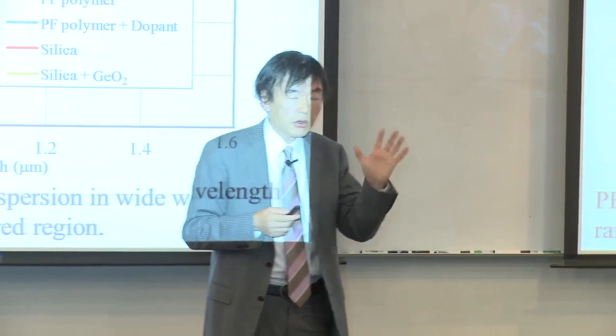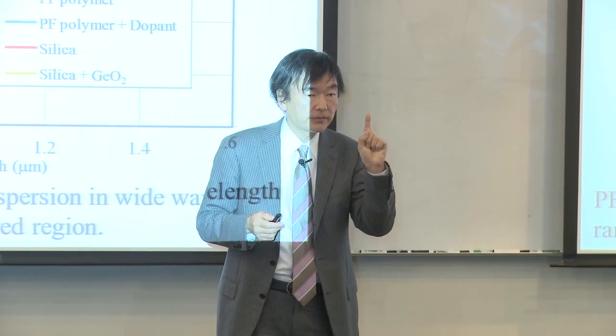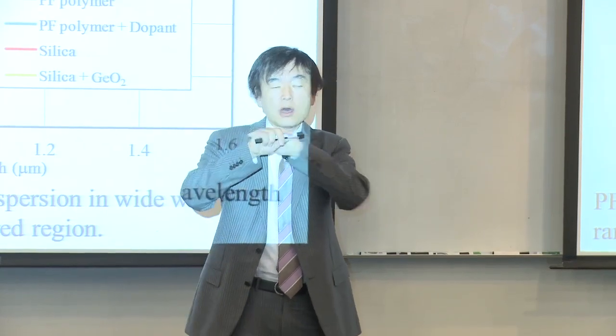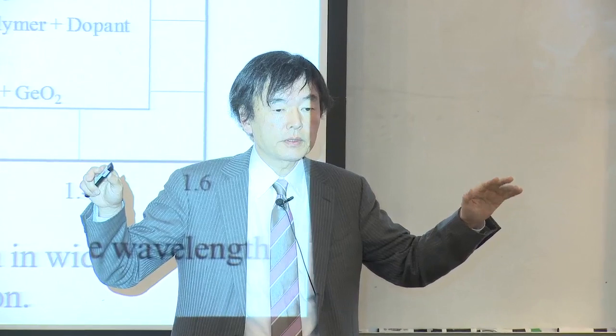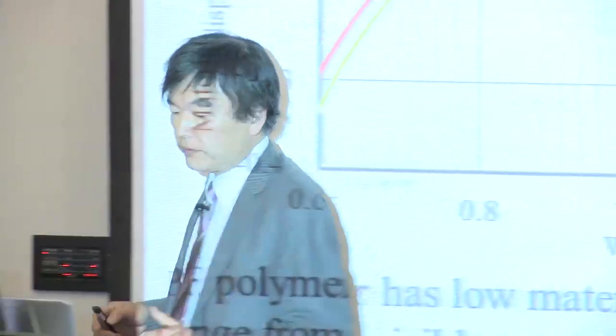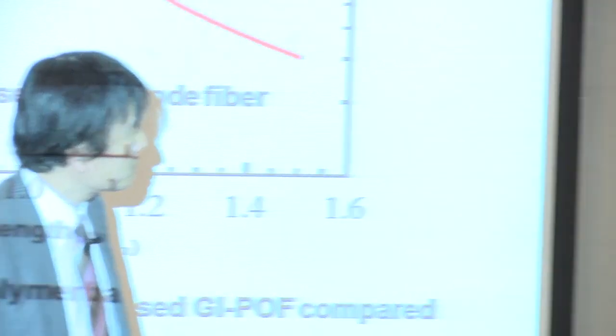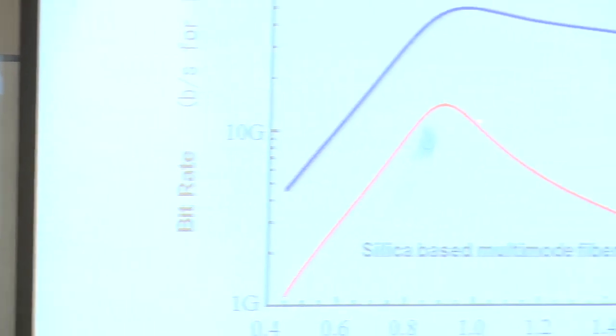So zero material dispersion is the ideal material. That material has no wavelength dependence of refractive index. If the refractive index is independent of the wavelength, then material dispersion is zero. So this figure shows the inherent characteristics of the material itself. Using this experimental result, we estimated the theoretical bitrate of the perfluorinated graded index plastic optical fiber. That is much, much higher than that of the silica multimode fiber.